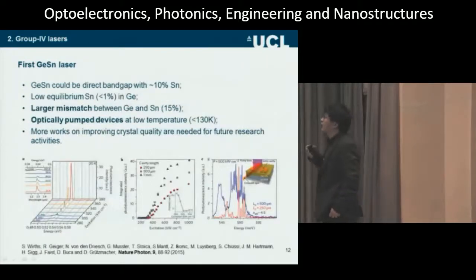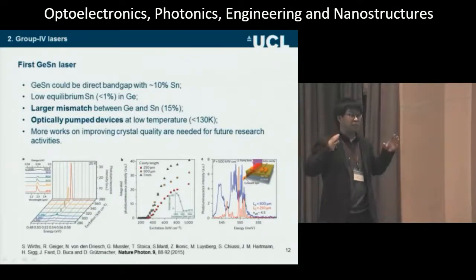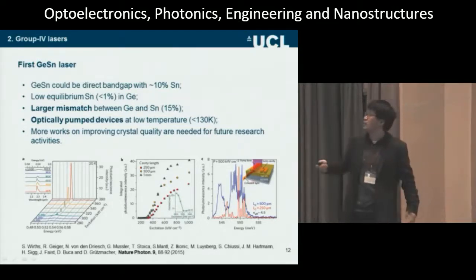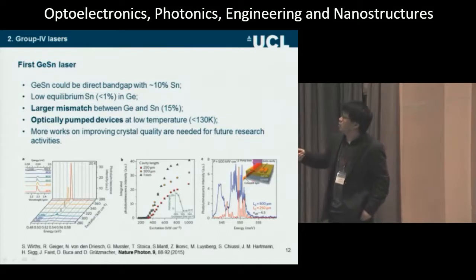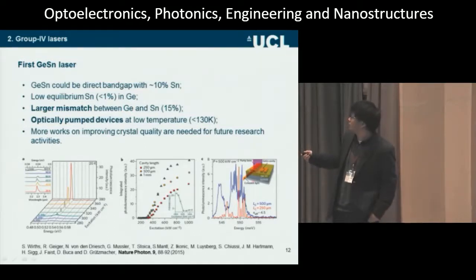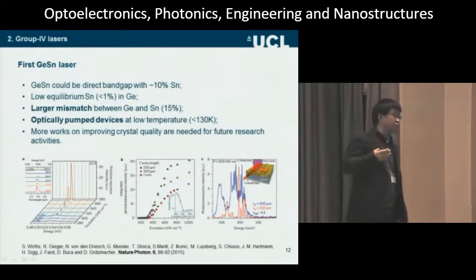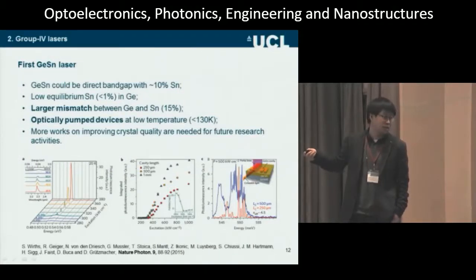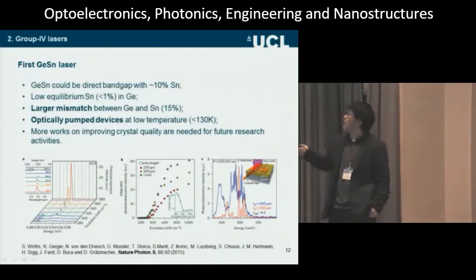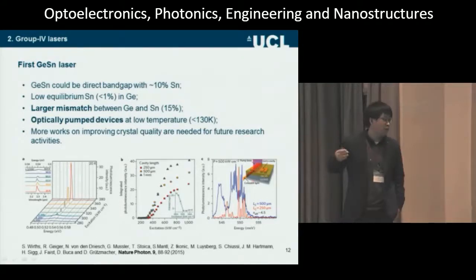Very recently, there's another new material called germanium tin. Because if you put a little bit of tin in germanium, you can potentially make a direct bandgap material. This idea makes a lot of group 4 guys very excited. Even for us, we also bought a new MBE and tried to grow germanium tin. But you also have a problem, it's a larger mismatch. This paper was published roughly 3 years ago. They got an optically pumped laser at about 90 Kelvin, a big achievement, the first direct bandgap material from group 4, published in Nature Photonics. Until now, I saw them last year, and they only got optical pumping at a little over 130 Kelvin.